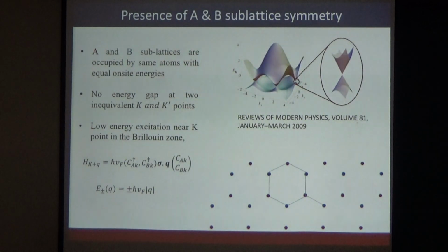And what has been found is that if I do a tight binding approximation, and if I write down the full Hamiltonian without any approximation, we can show that if I put the value of this k and k prime, the energy gap at these k and k prime vanishes. And then if I zoom in on this part, and if I expand that Hamiltonian near one of these k and k prime, where let's say k equal to capital K plus q, so that q tends to 0, q is very small, then we can write down the Hamiltonian in this form, where if I just diagonalize it, we get the band structure, which is very close to this k and k prime.